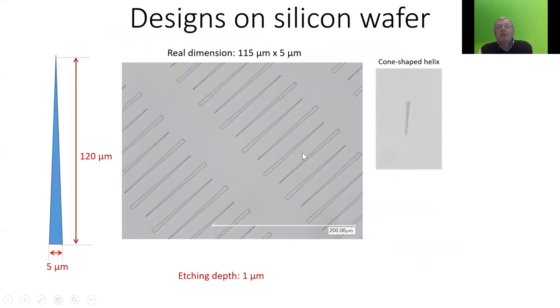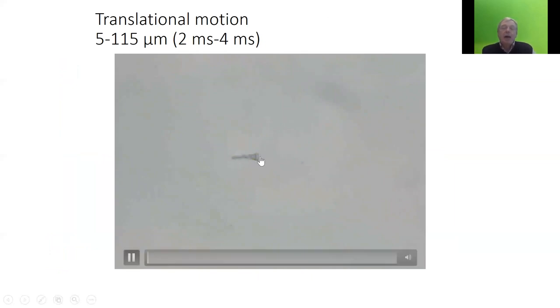You also can do this with a wedge in here. Now, you see this is a hydrogel in this wedge type form. And if you put it into water, you let it swell, it forms a helix. And actually, because of the wedge, the helix is conical in there. And when you now irradiate it with stroboscopic light, it will start to move because it decoils and recoils again. And because it knows its head and its tail, it moves forward in its own direction in here.